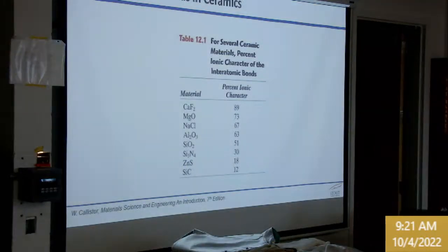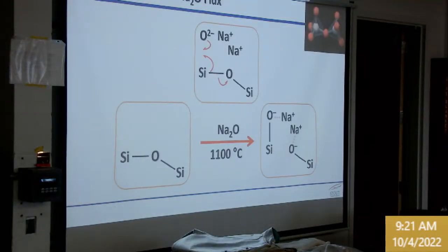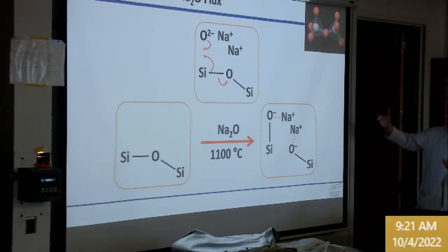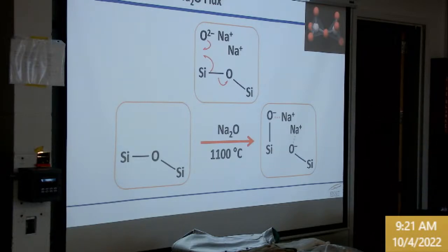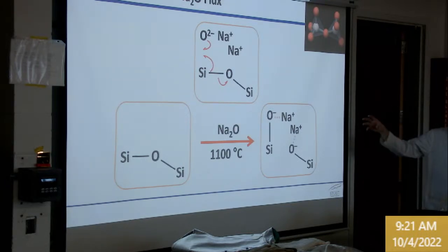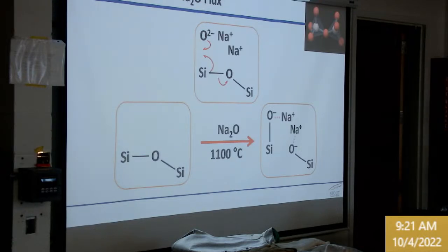Well, if we start messing up all those bonds, well, it's no longer going to be a crystal structure. It's going to turn into a glass that's going to behave in many respects like the parent crystal structure, but now it can no longer crystallize because the bonding regularity has been interrupted by all the ions. And we put in a lot, 90 grams of silicon dioxide, 50 grams of sodium carbonate, 25 grams of calcium carbonate. That's going to severely mess up the silica crystal structure.